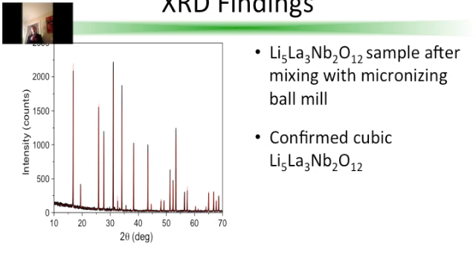Fortunately, synthesizing cubic lithium lanthanum niobate turned out to be much simpler than synthesizing lithium lanthanum zirconate. I only had to mix the reagents with a micronizing mill, heat them at the proper temperatures, and was immediately able to get it in the cubic phase. As you can see, the experimental data fits very nicely with the model in the X-ray diffraction pattern, with almost no amounts of the lanthanum zirconate oxide. So this was a pretty straightforward synthesis.